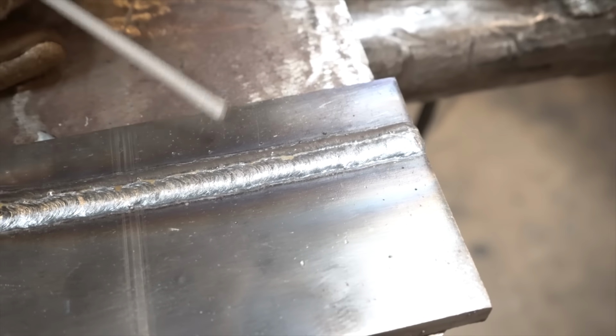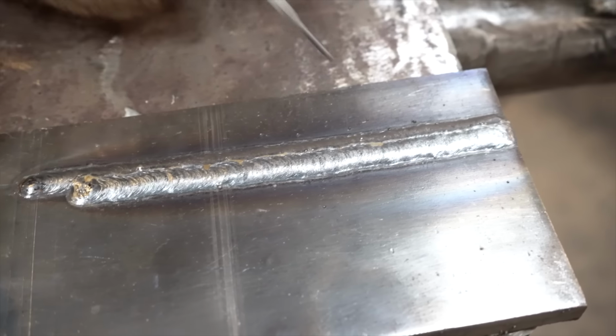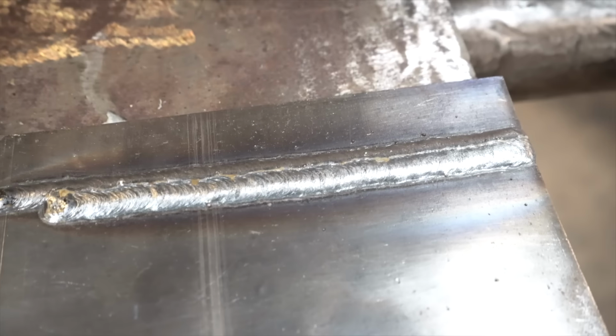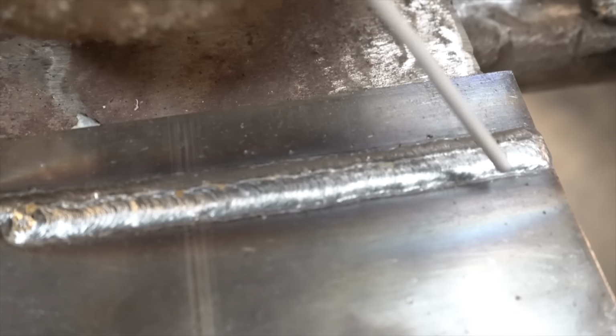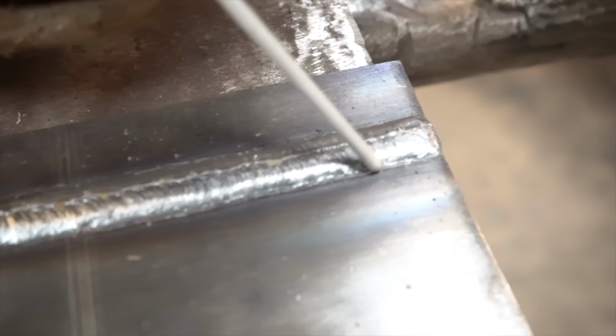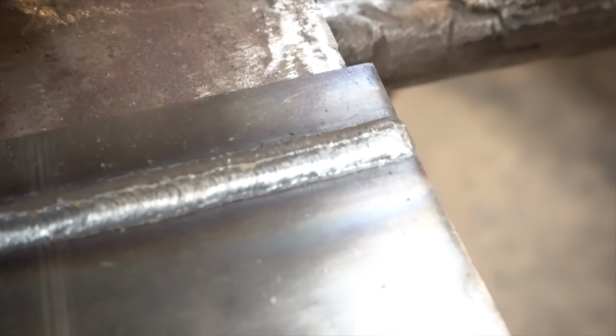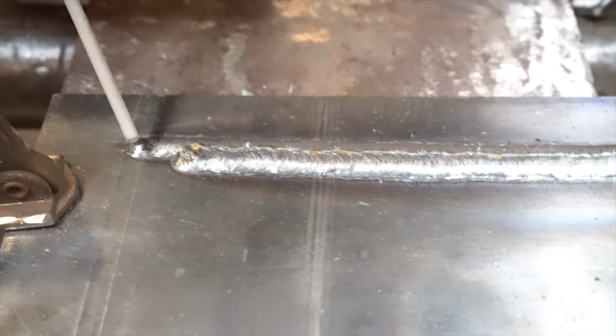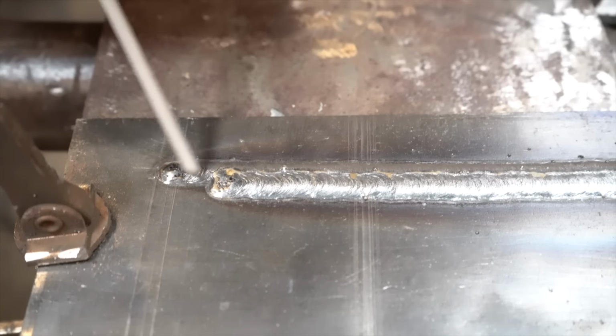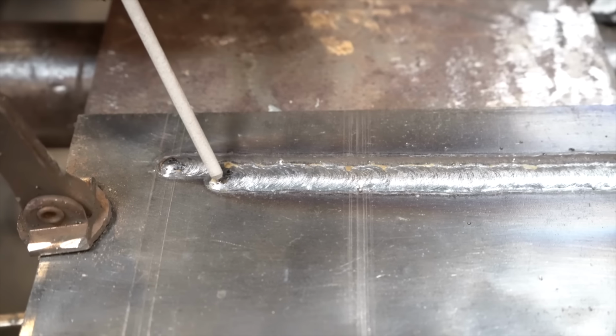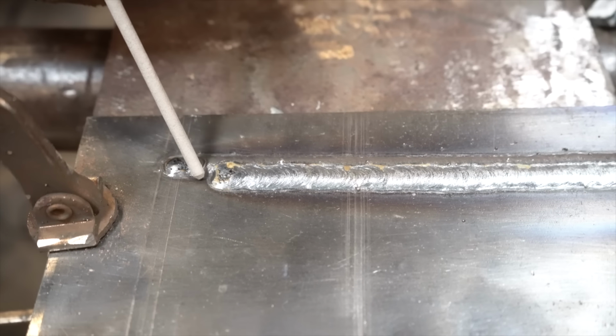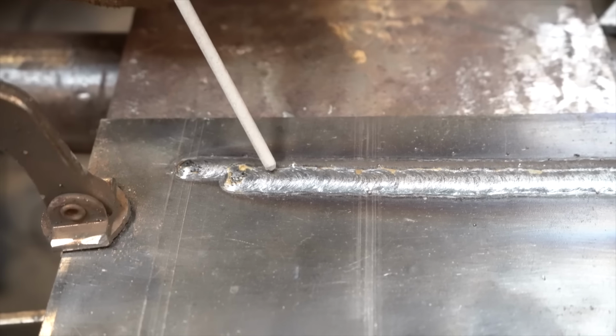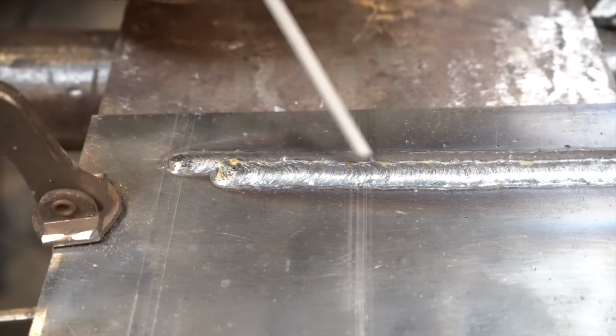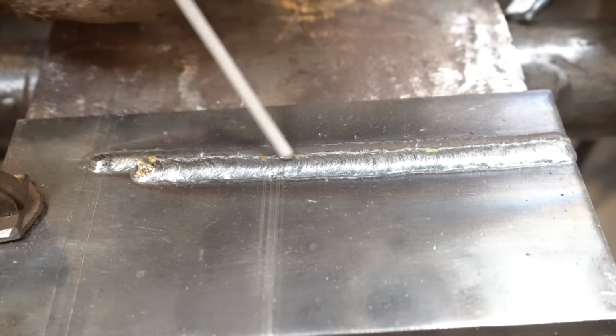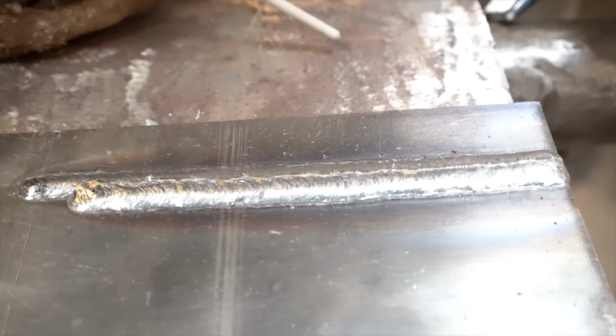So now talking about the overlap. Again, all I did with my electrode was keep the tip of that electrode right on that top edge of this first weld. My puddles, if you look at my puddles here at the end of the weld, are about the same width and length. And by keeping that tip of that electrode on that top edge, that gives me the 50-50 overlap all the way down across my weld.